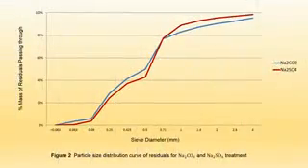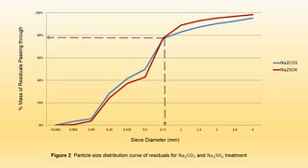From the results of sieve analysis, sodium carbonate is capable of weathering rock into finer residues than sodium sulfate when particle size falls below 0.71 mm, and these finer parts account for more than 3/4 of the total residues.